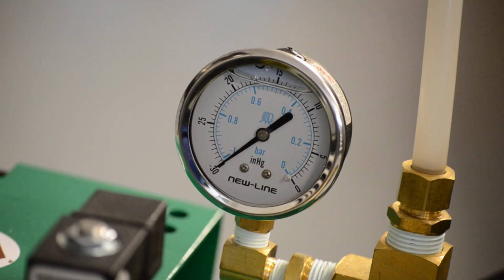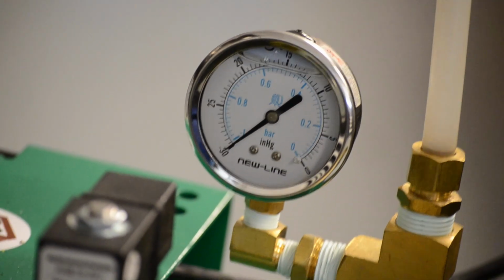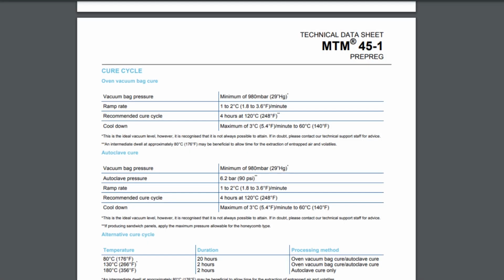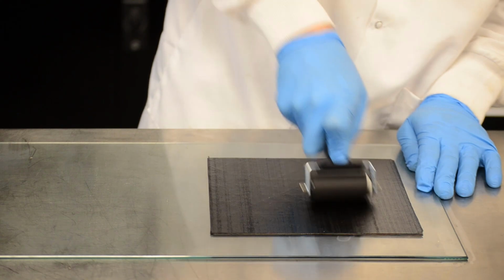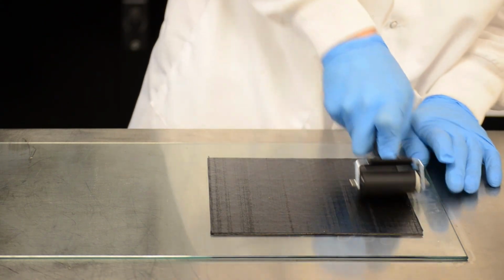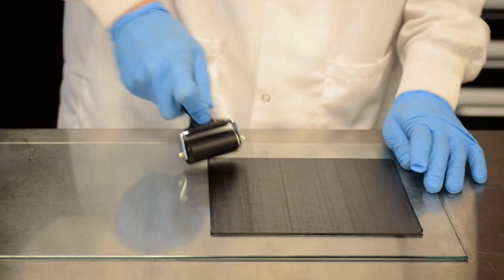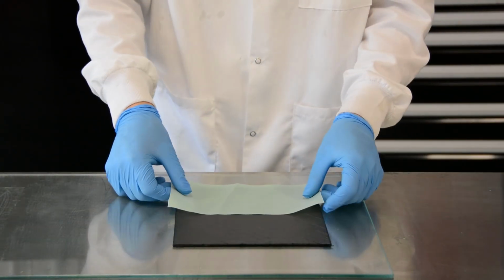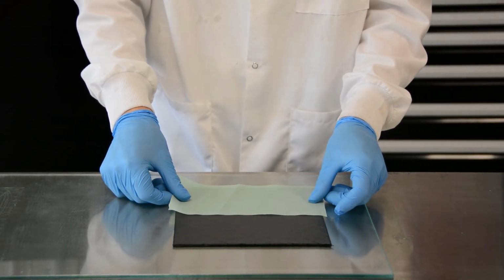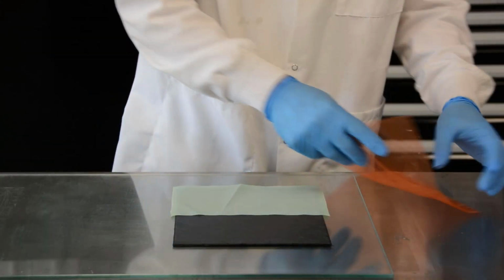Debulking time will depend on the application and material. It is typically 30 minutes or longer. Recommendations may be included on the material data sheet. After all plies have been placed, the vacuum bagging consumables will be installed. For this video, we will place peel ply on half of the panel to observe the surface finish it produces. Release film is placed over the entire panel.